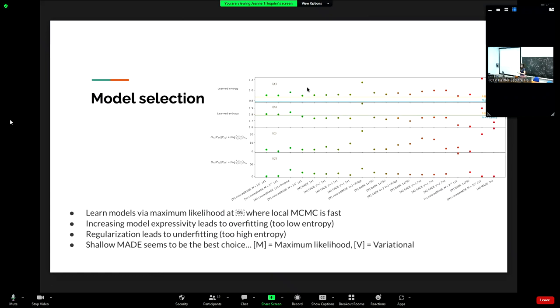But it was already a little bit surprising because we saw that the best models were the shallow ones. We tested also deeper models and some models with smart architecture like graph neural networks, and the best models were still the shallow ones. We saw that increasing model expressivity leads to overfitting, and you can see it because the entropy is too low. And regularization leads to underfitting. But okay, at least at this temperature, it was working. We had a good acceptance rate, a good reproduction of the thermodynamic observables.